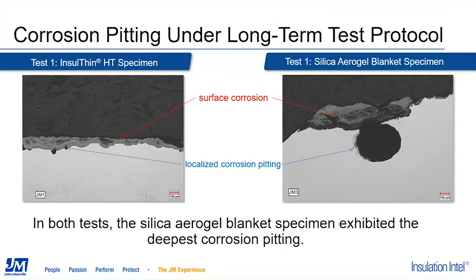So what you're looking at, the black area at the top, that's going to be background noise behind the actual test sample. The white at the bottom of the picture there is going to be the actual pipe itself. The red line's pointing to that surface corrosion riding on the top of the pipe. The blue line is pointing to that actual localized pitting corrosion, so that pit that extends into the metal. And we can see on the InsulThin sample, it's relatively small.